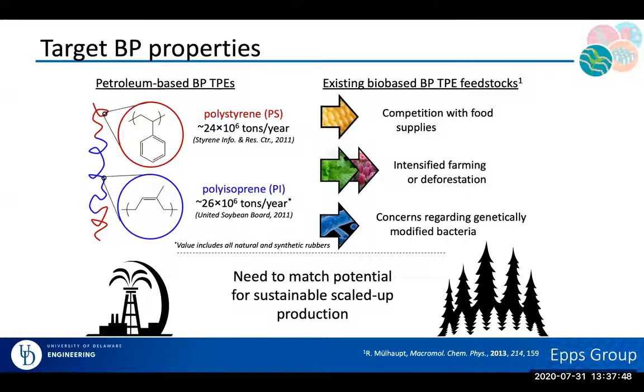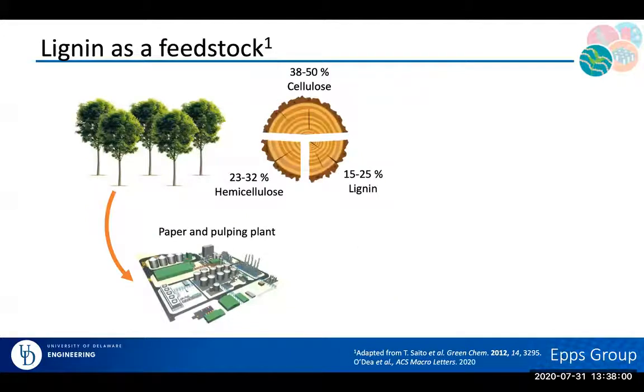So basically, there needs to be a better option that allows us to match that sustainable scale-up potential without competing with food supplies or otherwise further harming the environment. So in our particular case, we decided to use lignin as a feedstock. One of the reasons for that is because if you look at current pulp and paper mills as well as biorefineries, lignin is essentially a waste product of that process.